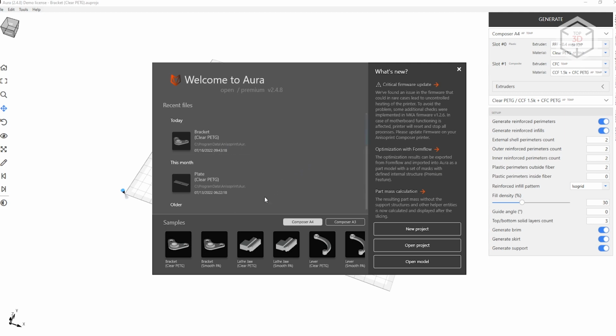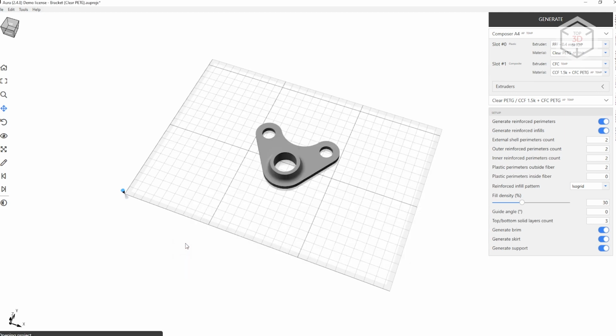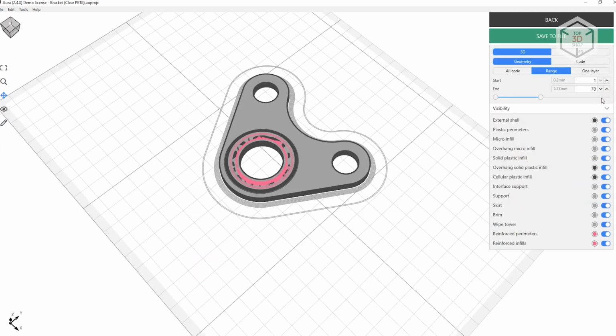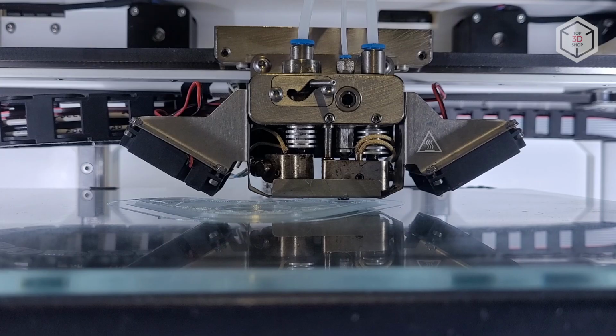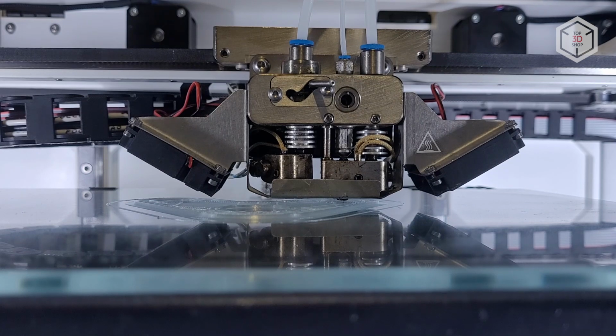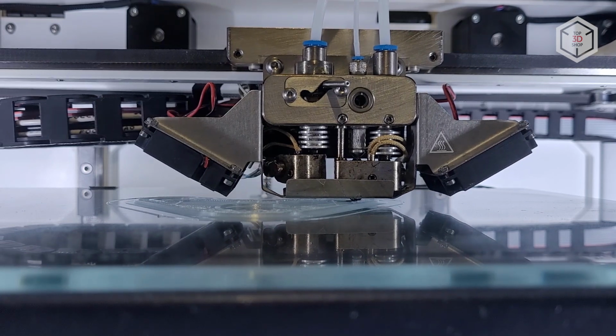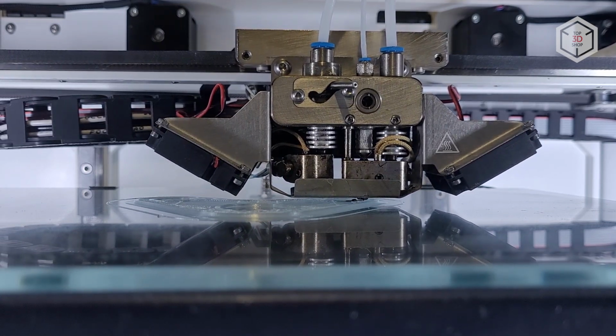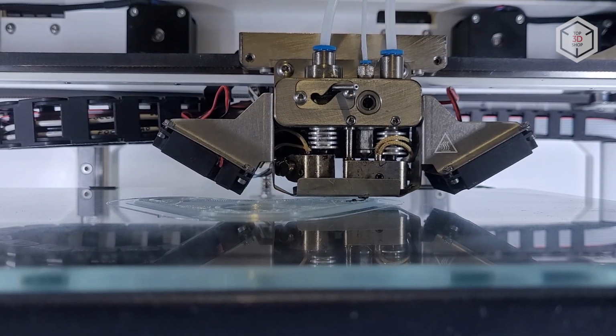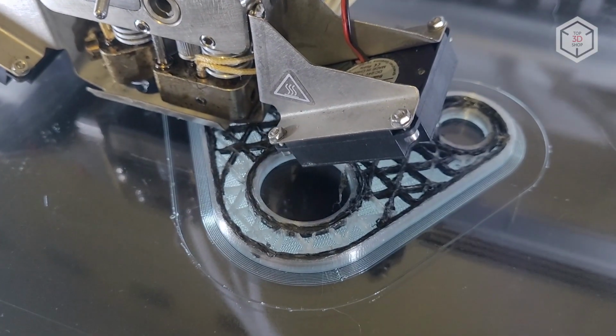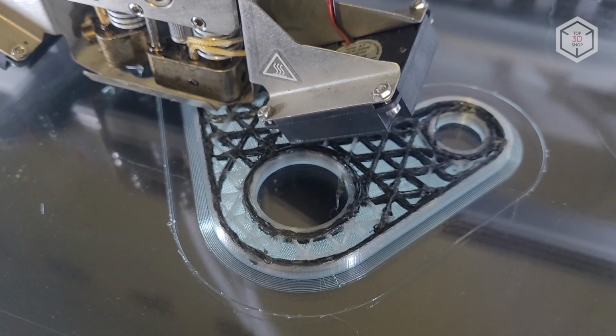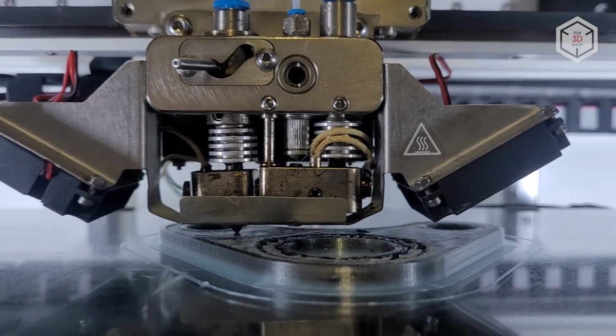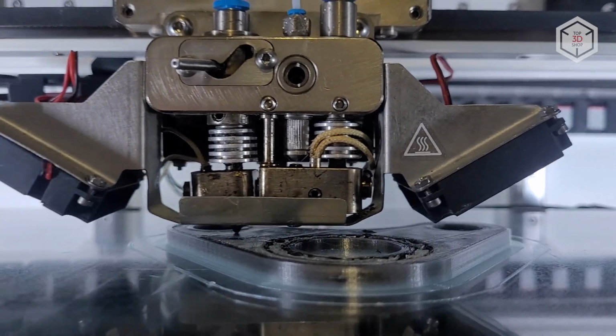So we took PETG filament along with carbon fiber and tried to print one of the examples that the slicer offers at the start. This is a small part with 3 holes. No major problems were encountered during the process. There were some moments when the fiber would slightly bend next to the nozzle at the beginning of a new layer. We may have done something wrong while calibrating the composite extruder. It didn't look very nice, but gradually these areas were covered by the upper layers and smoothed out. And the top plastic layers ultimately hid these flaws.